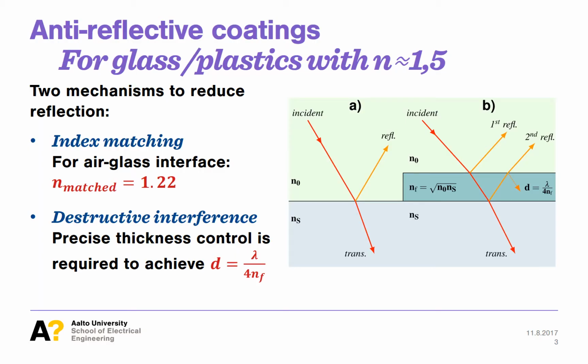First, I will refresh your memory on anti-reflective coatings. There are two main mechanisms to reduce reflection from an interface of two media. One of them is index matching. It reduces Fresnel reflection by introducing a film with a refractive index value between the index values of the two original media. The sum of the reflections at the two new interfaces, the first medium with the film and the film with the substrate, is lower than the reflection at the original surface.